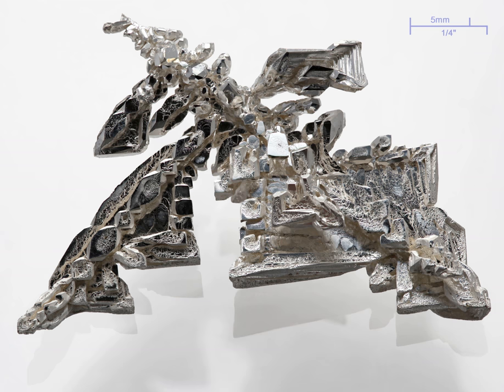The palladium isotope 107Pd decays by beta emission to 107Ag with a half-life of 6.5 million years. Iron meteorites are the only objects with a high enough palladium to silver ratio to yield measurable variations in 107Ag abundance. Radiogenic 107Ag was first discovered in the Santa Clara meteorite in 1978. The discoverers suggest the coalescence and differentiation of iron-cored small planets may have occurred 10 million years after a nucleosynthetic event. 107Pd–107Ag correlations observed in bodies that have clearly been melted since the accretion of the solar system must reflect the presence of unstable nuclides in the early solar system.